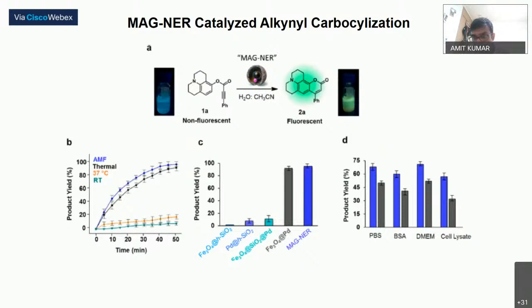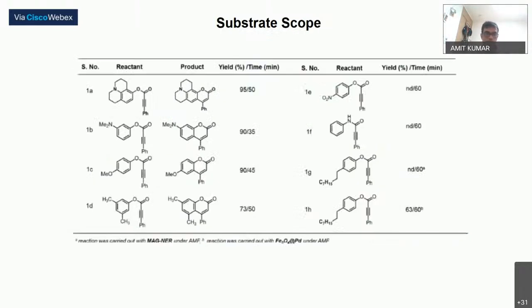Then finally, we also conducted these reactions in complex media, for example, various buffers or protein solutions, including cell growth media. And we saw that there is no effect on the reactivity of the nanoreactor, because in the complex media, proteins cannot approach to the catalytic site. So these are potentially very useful for biological applications. This is a substrate scope. So we could convert various substrates into the cyclized product within 1 hour, all the reactions. And the bulk temperature was very, very low, which is good for biological applications.